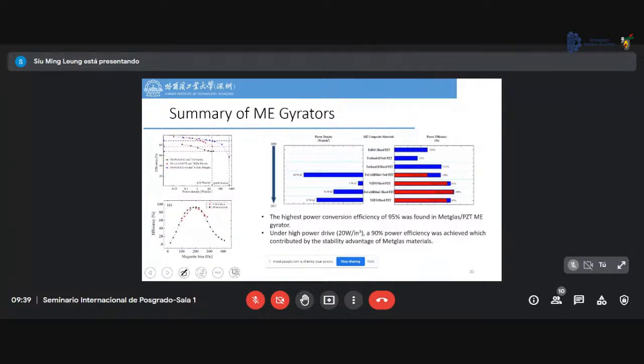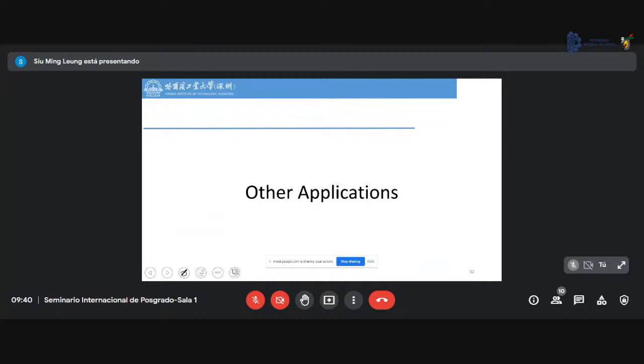So let me give a short summary of the ME gyrator. We tried different types of materials, say TFLD, nickel zinc ferrite, or ETM dot nickel zinc ferrite. And finally, we find that if we replace the nickel zinc ferrite by the Metglas material, we can get the highest power conversion efficiency, about 95%. Even though we drive it in a very high power region, it can still remain at 90% of the power efficiency.